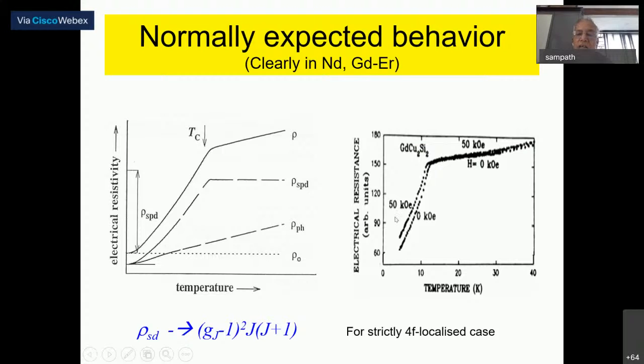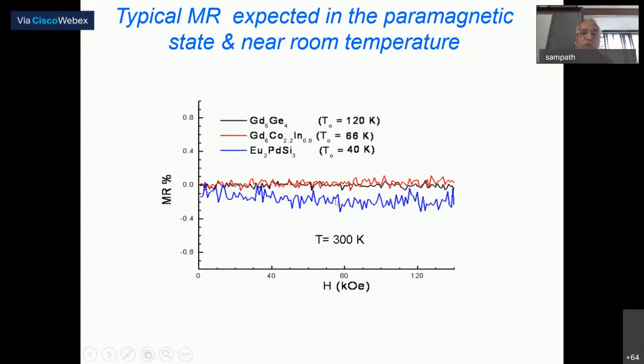Of course, magnetic orders can be a bit more complicated depending upon the nature of the magnetic structure, which I will not talk about. Therefore, if you measure as a function of field, I'm showing some examples here. Magnetoresistance as a function of field, for the fields which you can apply in your laboratory, typically 16 Tesla or 20 Tesla, you will not see any change in the electrical resistance. I'm just showing the experimentally measured data here for some material. This is supposed to be the normal behavior.